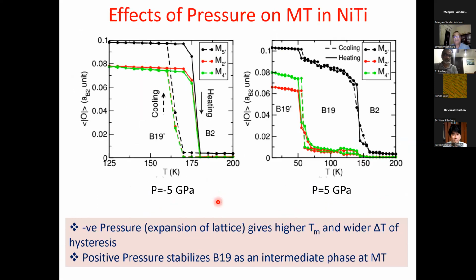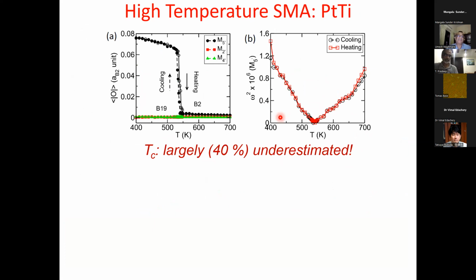We looked at pressure dependence of phase transition. See, this is again a luxury of the simulation techniques. We can look at phase transitions, how they change with pressure, both negative and positive pressure. And we see that you can change the nature of the phase transition itself by stabilizing another phase between the high temperature and low temperature martensitic phases. So indeed, these phase transitions are sensitive to pressure, but the TC was 40% underestimated.